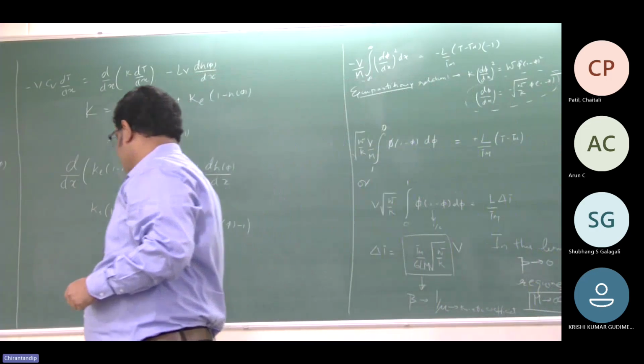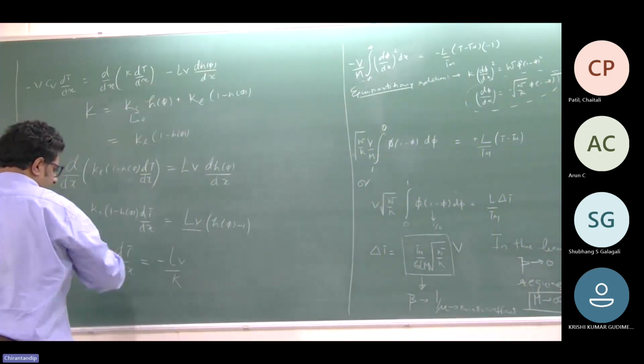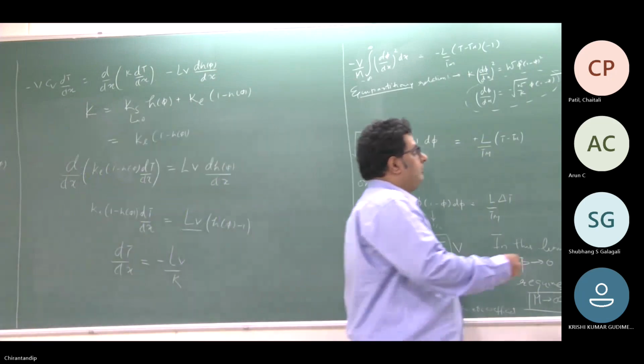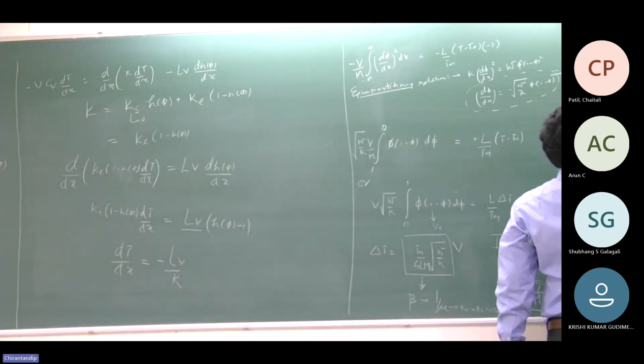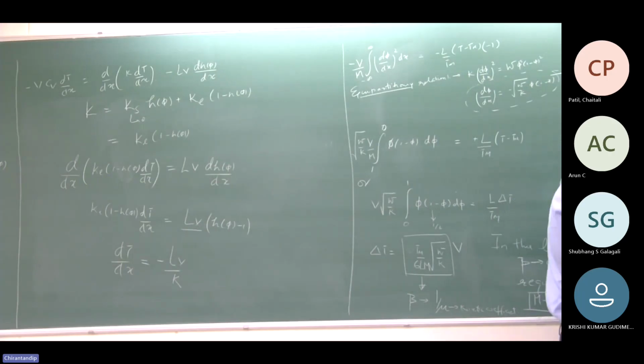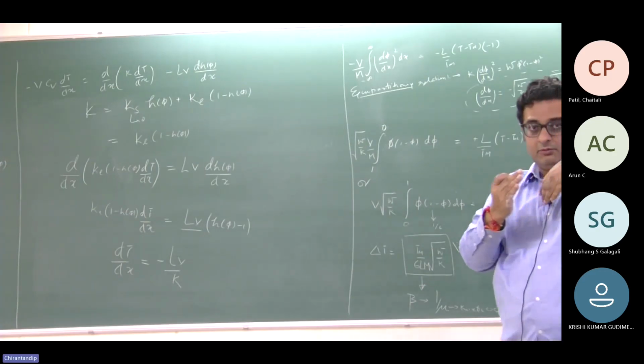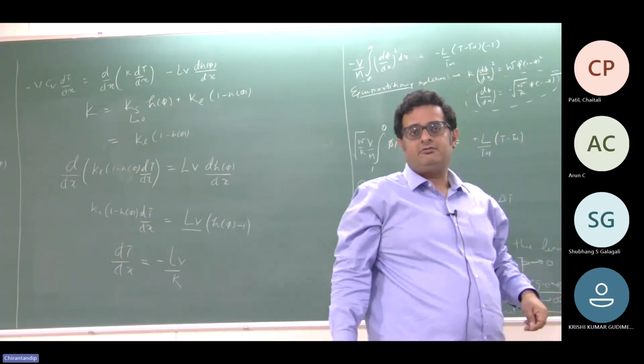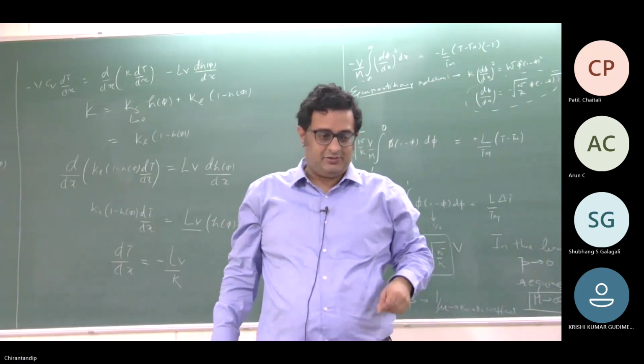Right? So what we learn from this is, because of this factor, you essentially have a situation that if they don't match here, the mismatch will be small, but that mismatch will scale as soon as I make the thing large. Right? So it's a direct function of how wide your interface width is. Right? And as I said, how fast the interface moves.